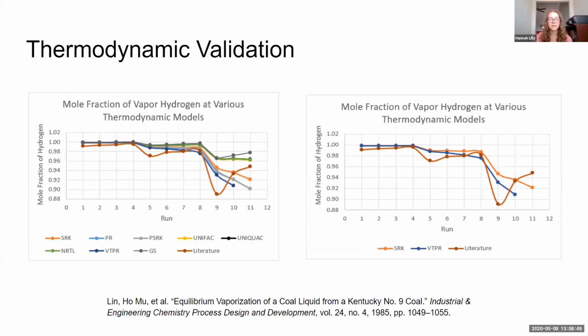The literature source here consisted of 11 different runs at various temperatures and pressures. It's important to note that run 10 had the closest temperature and pressure to what we're actually running in our reactor. So it's important that SRK had a good fit at that point specifically, which it does.